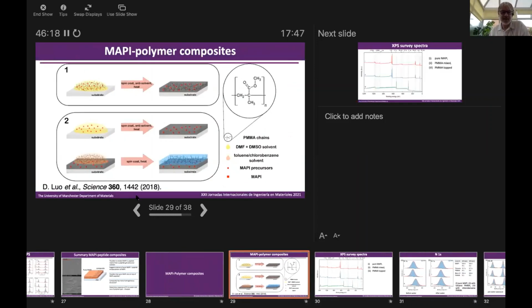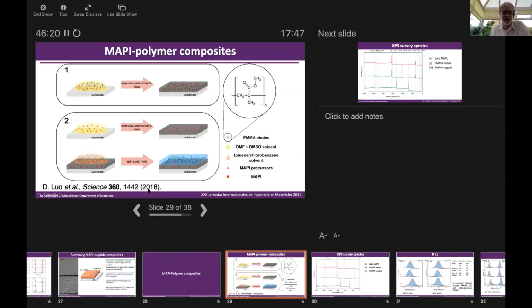So essentially, there was a paper published in 2018 by the Oxford group led by Henry Snaith, where they made an inverted perovskite cell, and they encapsulated the perovskite with PMMA by putting a layer of PMMA on top of the perovskite material. The idea there, obviously, was just to keep the water out. PMMA is quite a hydrophobic material, and you can just form a barrier. So rather than trying to improve the chemistry of something which all works very well, why not just try and keep out the moisture? So we've looked at two approaches to MAPI polymer composites.